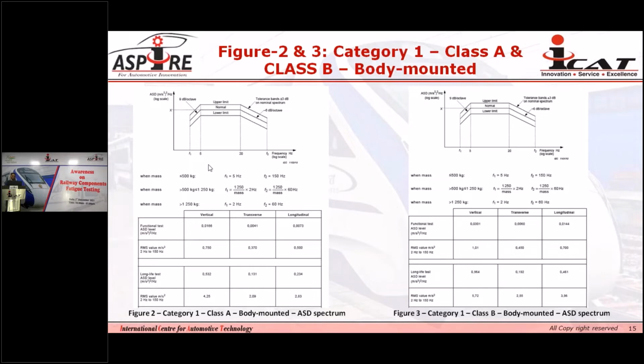So how will we select the test frequency band for a different weight of the test component? For this, the standard frequency band totally depends on the weight of the test component. For category 1 class A and class B, if the weight of the test sample is less than or equal to 500 kg, then the frequency band will be 5 to 150 Hz. If the weight of the test sample falls between 500 kg and 1250 kg, in that case there is a formula to calculate the lower frequency and higher frequency. To calculate the lower frequency, we can use this formula: 1250 divided by mass of the test sample.